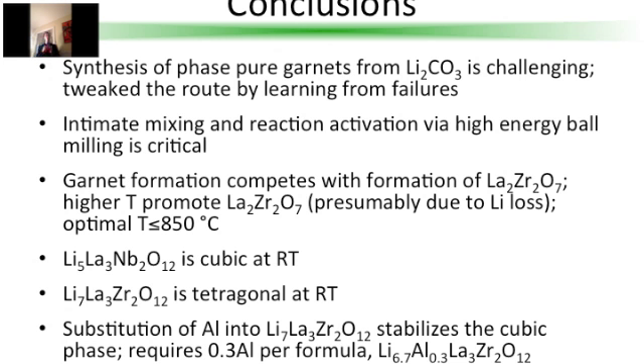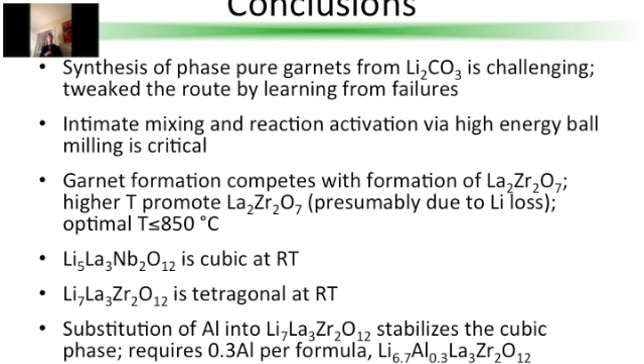I also found that lithium lanthanum niobate stabilizes in the cubic phase at room temperature, while lithium lanthanum zirconate stabilizes in the tetragonal phase. So to get lithium lanthanum zirconate in the cubic phase, I concluded that it is necessary to insert aluminum into the sample, and I used 0.3 aluminum per formula unit to obtain Li 6.7, Al 0.3, La 3, Zr 2, O 12.